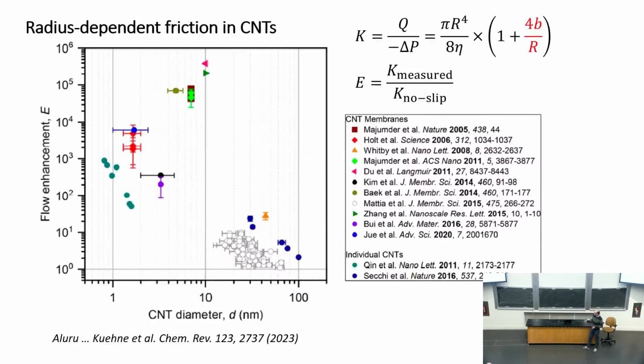Okay. Now, this is a plot I assembled for a review that we recently published, where I look at friction measured in CNTs. Here the CNT diameter is very big and becomes smaller, and you see that as the diameter gets smaller, the flow of water through these CNTs becomes enhanced. By enhancement, it's basically just the ratio of the measured permeability versus the no-slip permeability. And the difference here is actually just defined by the slip length. So you go smaller in radius, your flow enhances, which means your slip length enhances. So how can this be understood?